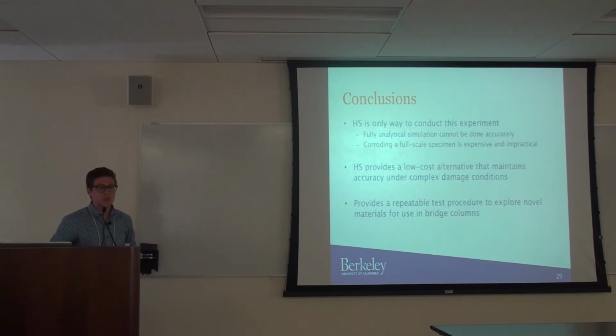So just to circle back to our original experiment, we saw that hybrid simulation is really the only way that we can test these specimens and get this data on corroded bridge columns. And that hybrid simulation is a low-cost alternative, and we do get accurate behavior of the damaged section. And then it's a repeatable test. So like I said, going forward into this high FRC test should be rather straightforward.